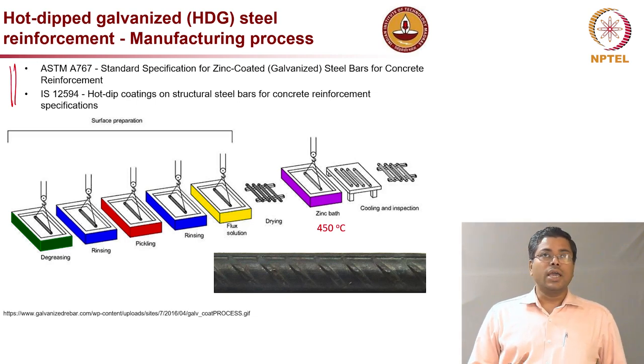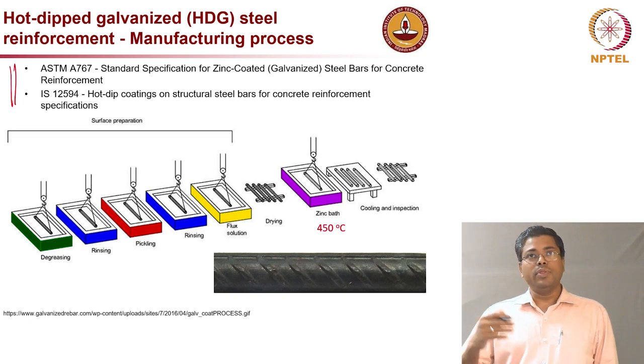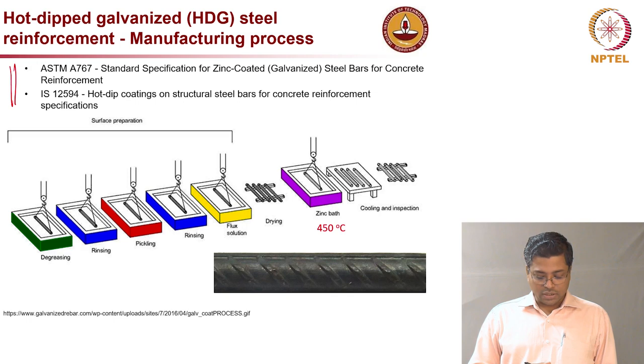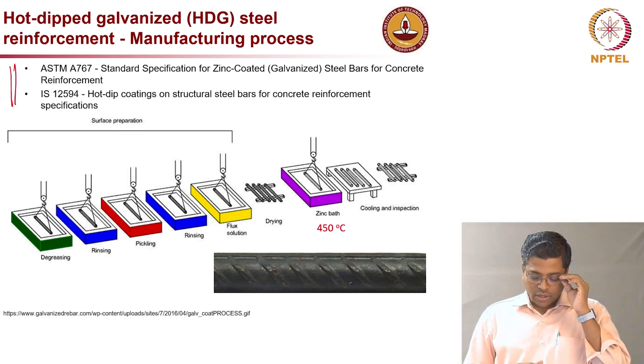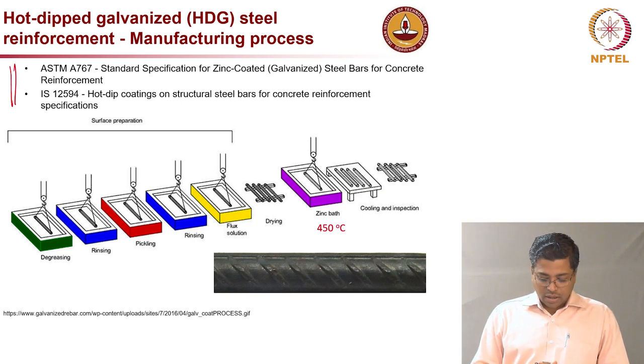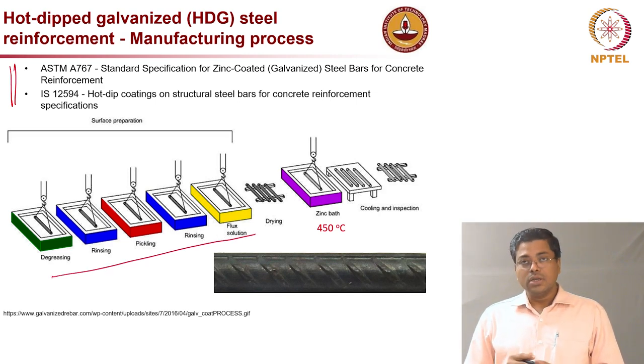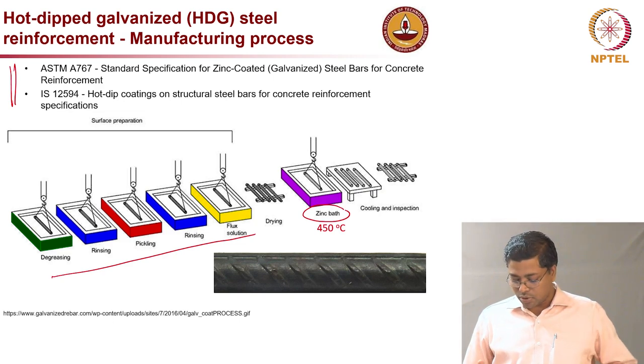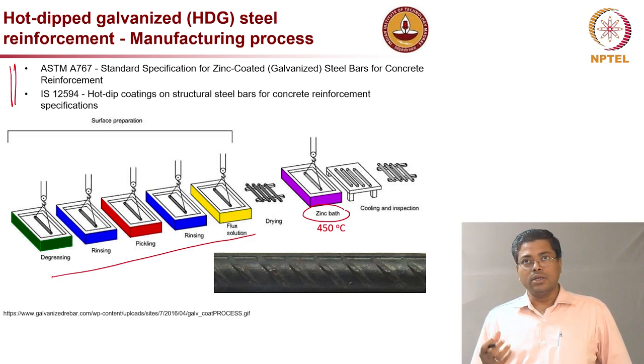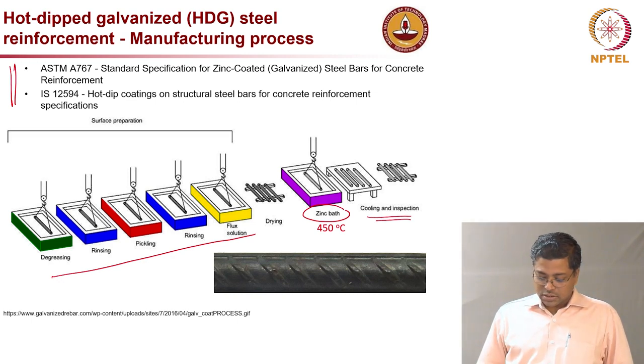How is galvanization done? First, the rebars are cleaned — when they reach the galvanization unit from the steel mill they may have dirt, soil, or oil. The metal surface must be very well prepared and cleaned. Then the steel bar is dried and immersed into a zinc bath at approximately 450 degrees Celsius. The zinc adheres to the steel surface, then it is allowed to cool and undergo further inspection before leaving the factory.